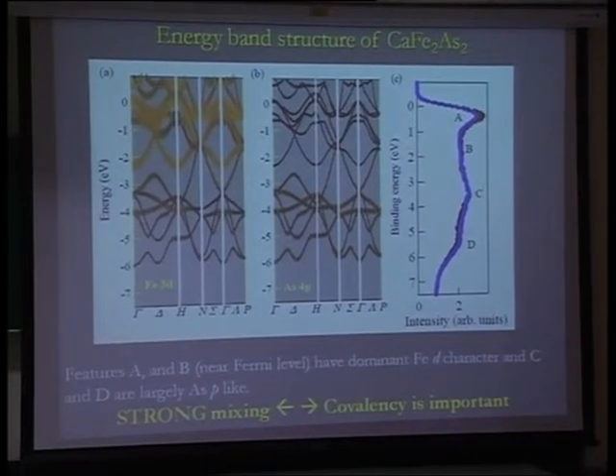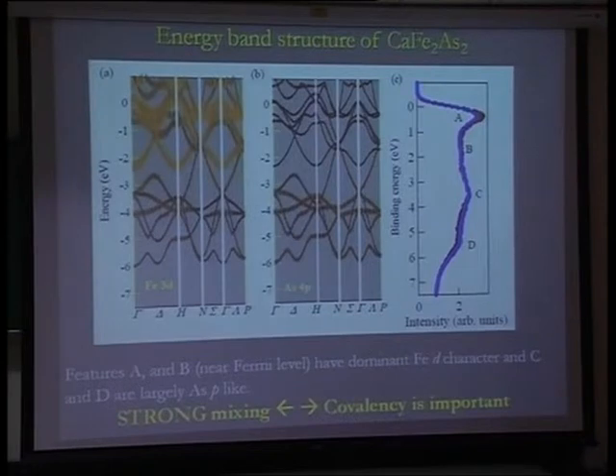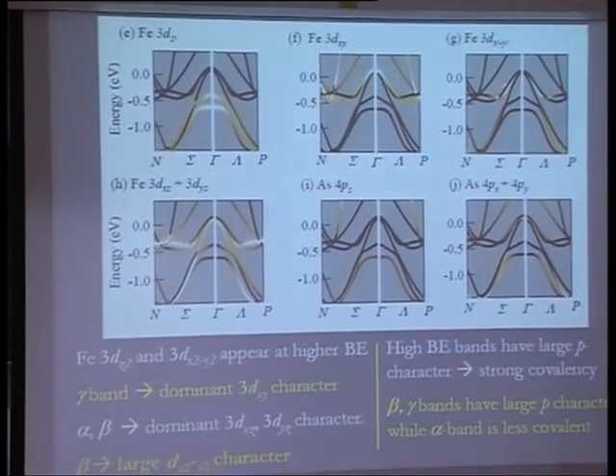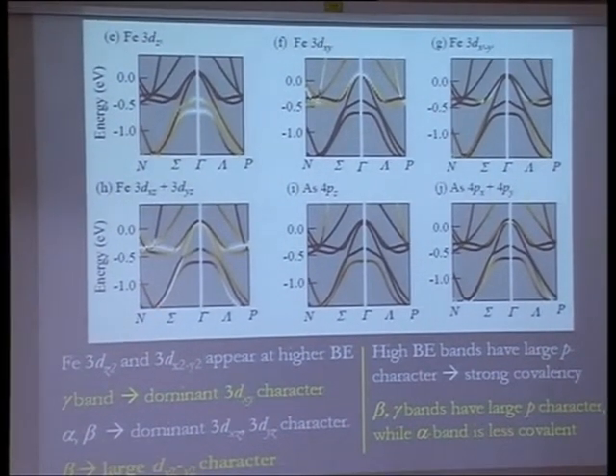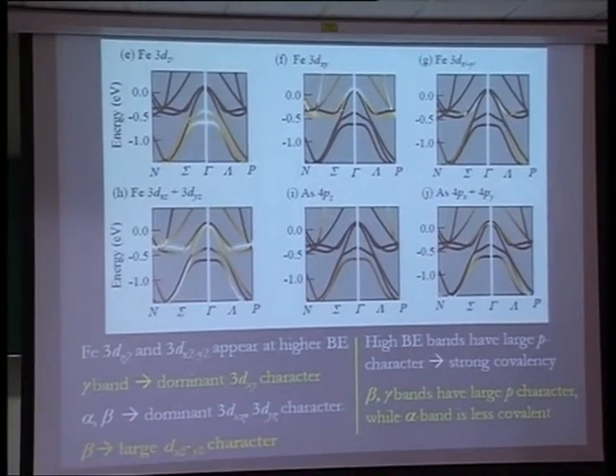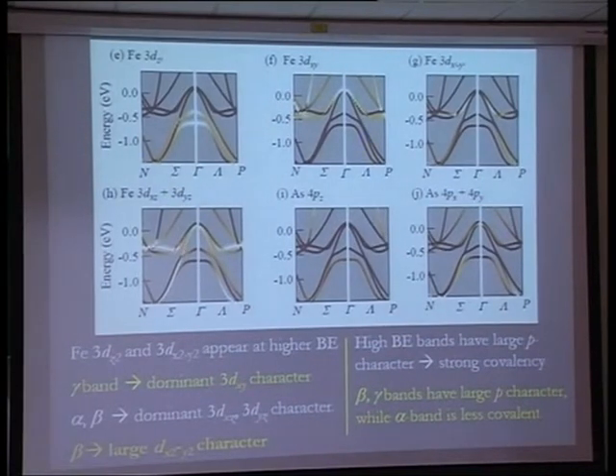Now you can look at the energy bands, which I have shown as alpha, beta, gamma. The 3D z square appears around this energy range, and this alpha, beta, gamma, which is coming here close to the gamma point, you can see this one is alpha, this one is beta, and this one is gamma, and they have different orbital character. So the 3D xy is dominant in gamma, and alpha has strong dxz and yz, and the beta band has some finite contribution from 3D x square minus y square, okay? So these are the orbital characters that you see, and of course arsenic P also contributes here.